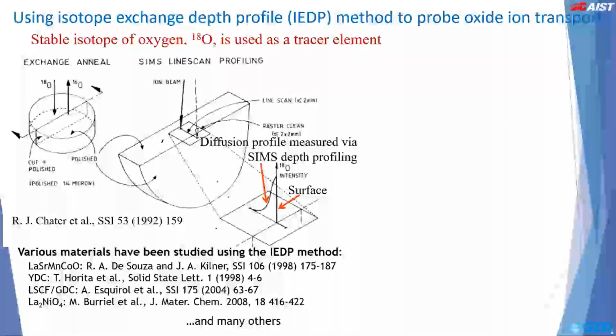To investigate the oxide ion transport through the cathode materials, we employ the isotope exchange depth profile method in conjunction with secondary ion mass spectrometry, or SIMS. This is a well-known technique that has been used to study a variety of bulk and thin film materials. Here, the sample to be investigated is isotopically exchanged by annealing in an enriched atmosphere containing the stable isotope of oxygen, 18O. The diffusion profile of the tracer gas is then obtained using SIMS depth profile analysis.